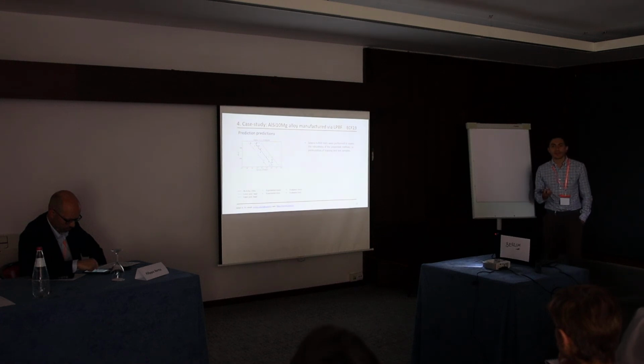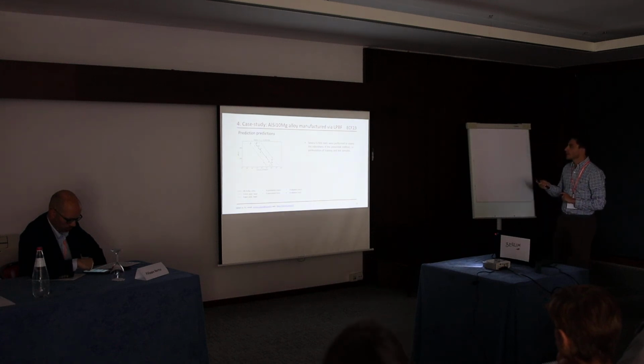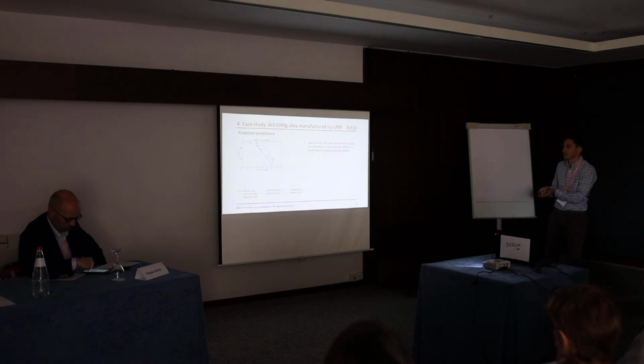So out of 12 samples, we used 10 samples to train the machine learning, the physics-informed machine learning, and we used 2 samples just to verify. It was a test sample. Okay. And then we also did a k-fold test. So we did some permutations of these 2 and 10 samples to actually assess the robustness of the method. So these are just 2 examples, but we did many.